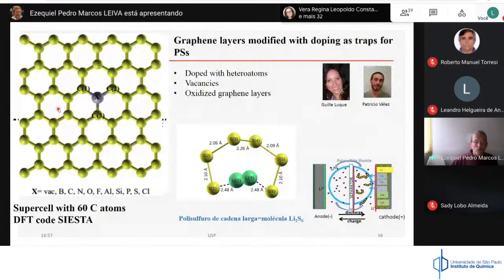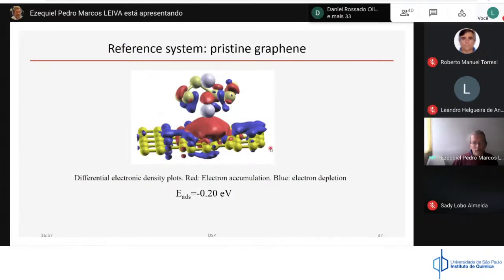Well, one of the things that we investigated with Guille Luque and Patricio Velez was the capacity of some modified graphene surfaces, modified by substituting them with atoms. We doped this surface with heteroatoms, and we analyzed the interaction of polysulfide with these heteroatoms. So we took a typical polysulfide, a 6-atom sulfur chain, and we considered the interaction of this molecule with these surfaces, doped or non-doped with these heteroatoms. We took pristine graphene as a reference system. We put this polysulfide interacting with the surface, and we calculated the energy.